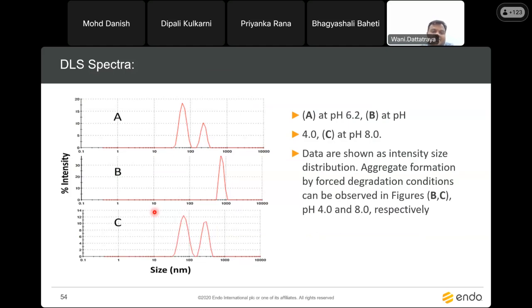This is some application of DLS spectra. Here the three spectra are A, B, C. A is at pH 6.2, B is at pH 4, and C is at pH 8. If you look at this size distribution at pH 6.2, your size is about 100 or near about 100. If you change the pH to 4, your size is about 1000. So what is it indicating? It is indicating that at pH 4 there is a formation of aggregates in your molecule. Same with pH 8. At pH 8 we can also see that there is denaturation or some aggregate formation. So from this data we can predict the optimal pH required for the formulation.